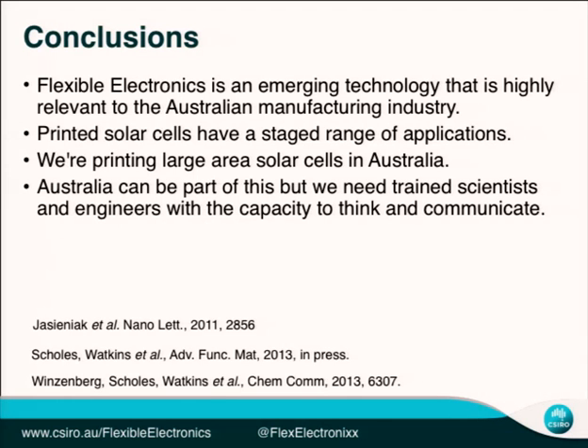What's the internal impedance like? Do you lose much of the energy in the material? The major loss point is actually at the electrodes. On the printed devices, the indium tin oxide we buy in, and its sheet resistivity is actually the limiting factor in the whole device. When we buy it on glass, we get sheet resistivities of maybe 5 to 10 ohm per square, but on the PET we're at 20 to 50 ohm per square, and that's what limits us to these 1 centimetre wide tracks too. But there are people working on that. We're not addressing that. We have to focus on the key areas that we can. As people develop, there are a lot of alternatives like silver nanowires, carbon nanotubes, graphene and a whole lot of other alternatives to ITO. There's no shortage of options in that regard.